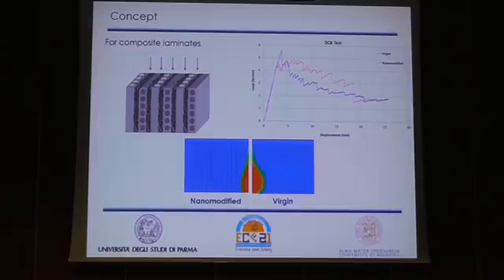Although the critical value of the energy dissipated in the nanomodified laminate is lower than the virgin one, the amount of damage dissipated energy increases as the impact event proceeded. You can also see a contour plot extracted from a finite element model showing some differences in the delaminated area extension between a nanomodified interface and a virgin one.